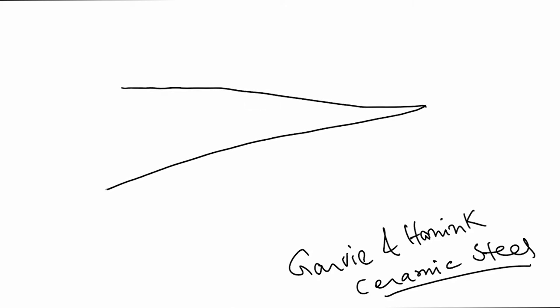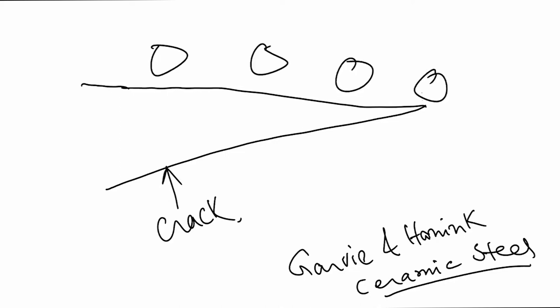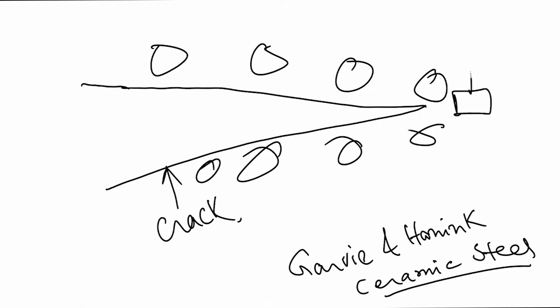And that causes a lot of enthusiasm in the community. In a simplistic manner, let me explain why tetragonal phase. Suppose this is a crack tip, suppose this is a crack. So around the crack face, if tetragonal zirconia is retained in the face, then a crack tip has a particular stress field, right, in the tensile stress field.